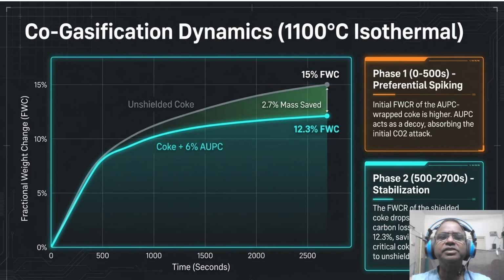And that's a good thing. The AUPC is acting as a decoy, absorbing that initial aggressive CO2 spike. By phase 2, the carbon loss stabilizes. By the end of the run, we have restricted carbon loss to 12.3%, saving exactly 2.7% of the critical coke mass compared to the naked operation. But it isn't just a surface area game. There is a chemical glaze forming that seals the deal.